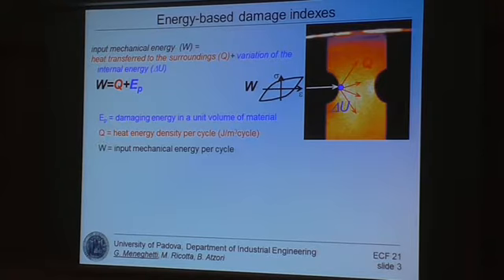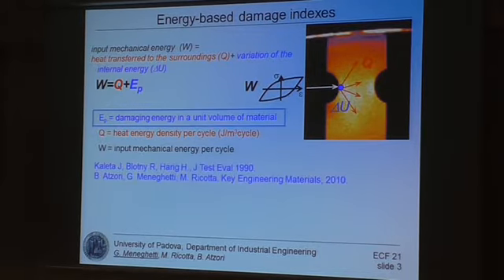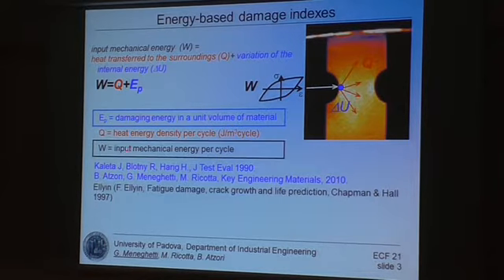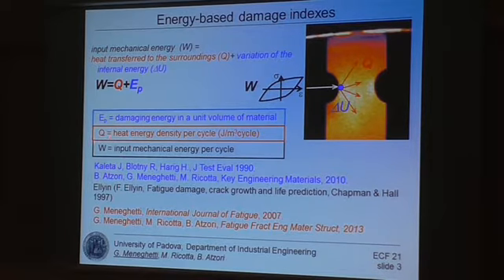So if you try to experimentally measure the stored energy of cold work, the measurement will be affected by high uncertainties. So in the past, Kaleta and co-workers with Professor Harig in Germany tried to measure the stored energy of cold work. We all know that Halford developed an approach based on the expended mechanical energy, but we tried to use the energy dissipated as heat to estimate the fatigue life. Of course, heat energy is only a manifestation of fatigue damage, it is not by nature the fatigue damage itself, but it is a fatigue damage index.